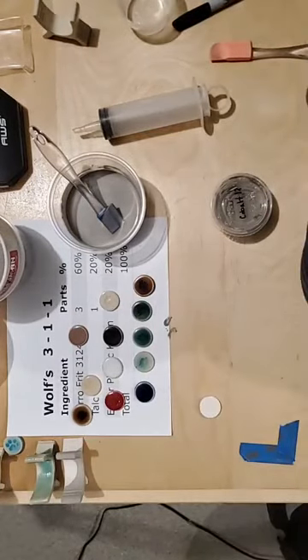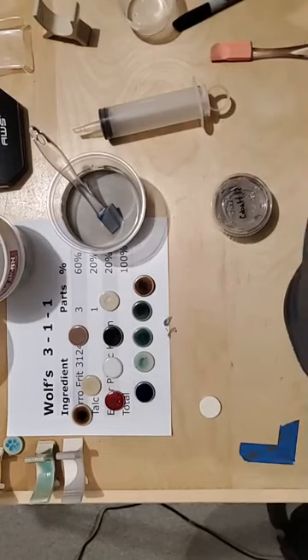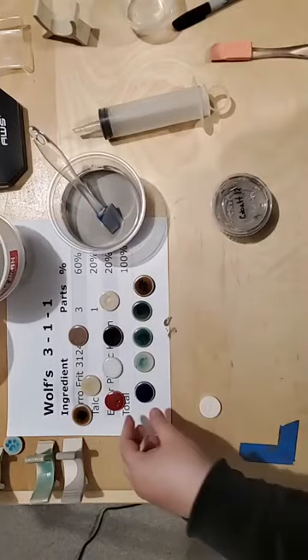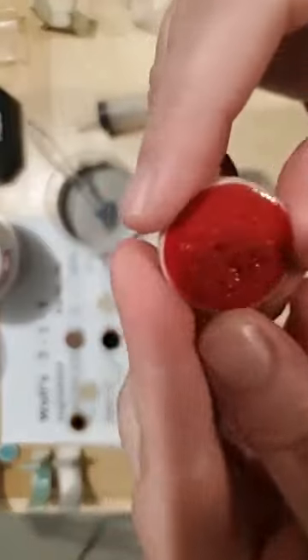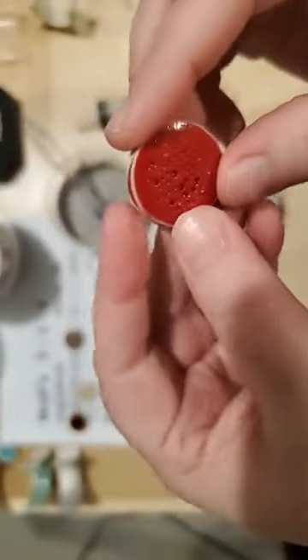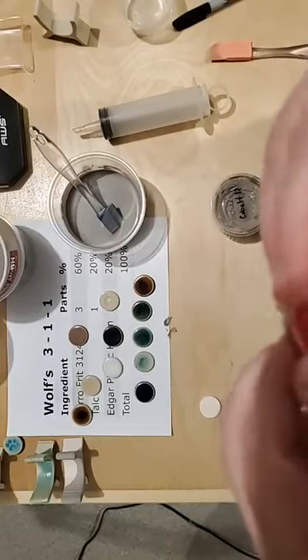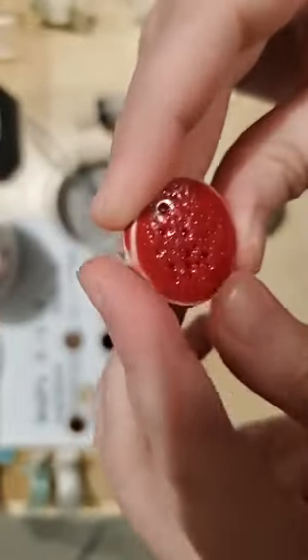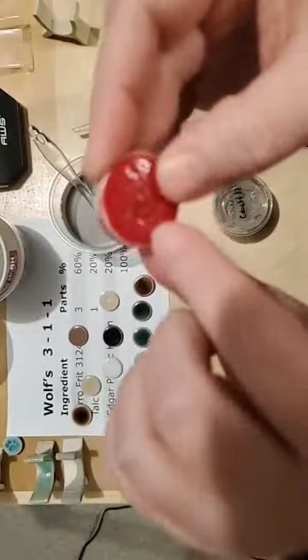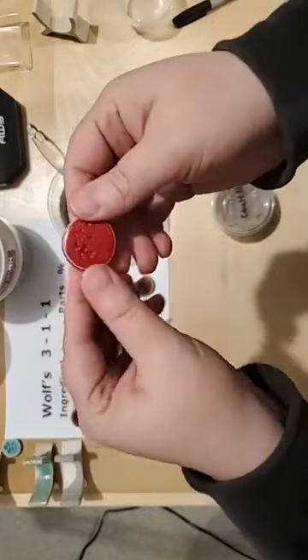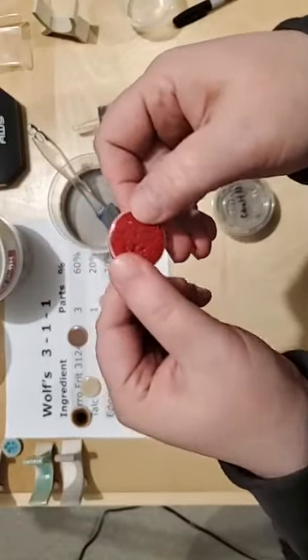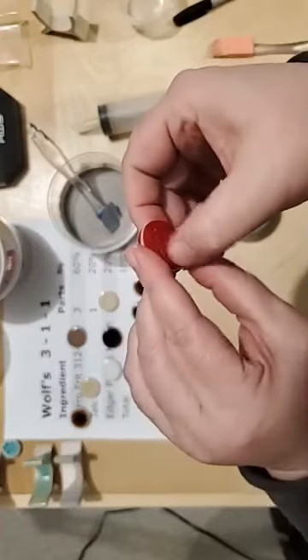The speckles are kind of nice. What is causing those little bubbles or pits in the little test tiles? So in some of them, you'll see, like for example, the mason stain. Mason stains are fickle creatures because they're encapsulated and they bubble up. So this one is likely the mason stain, and when I get up close looking at the mason stain one, it looks a hair under fired. Since I don't know what's in the mason stain, it's probably refractory, and it probably wanted to be melted a little bit hotter.